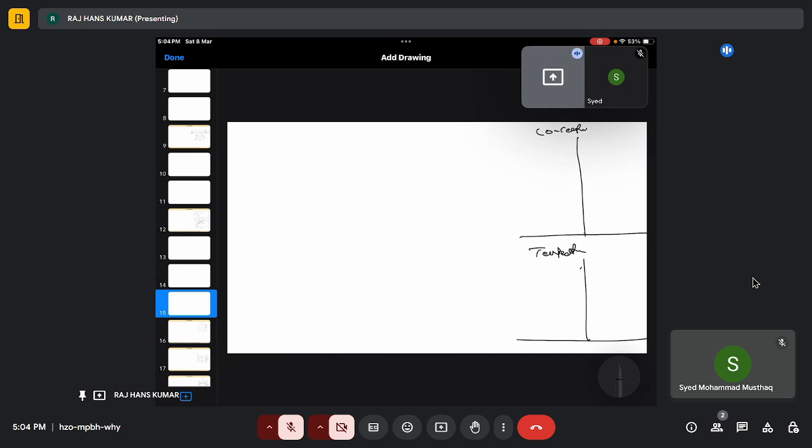And because of the rejection of solute, we will have it build up, and there will be a concentration gradient, right? So this is the XL, now what about the temperature? The equilibrium temperature is like this, and our thermal gradient is like this, right?